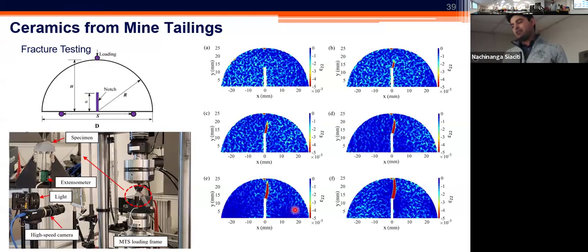Again, the beauty of the digital image correlation is that it provides you with the entire profile of the strain and the deformation on the surface. So by doing so, we were able to document and confirm that these tailing-based ceramics had also successful and similar fracture behavior to the sintered ceramics from natural resources like sand and clay. And yes, that's essentially where the research stands at this point. So we are hoping to find ways that we can take this to a next step and be able to apply the same methodology at the larger scale.